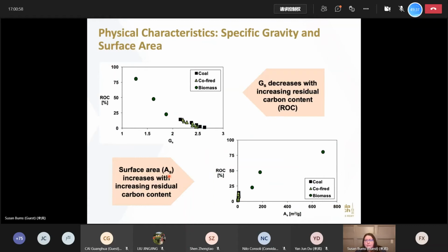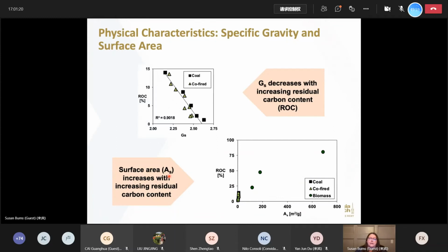So why is this? What's going on here, and what is it telling us? What we see in these cases is that our specific gravity is going to decrease as our residual carbon content increases. That's logical, right? Because the specific gravity of organics is somewhere around 1. So as we come in and look more closely here, if we zoom in and get a little bit close up on the finer scale, what we'll see, as long as we're in the coal range or the co-fired biomass at low percentages, we're going to have a reasonably linear correlation with specific gravity.